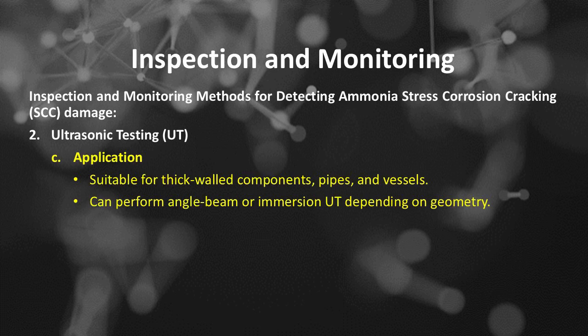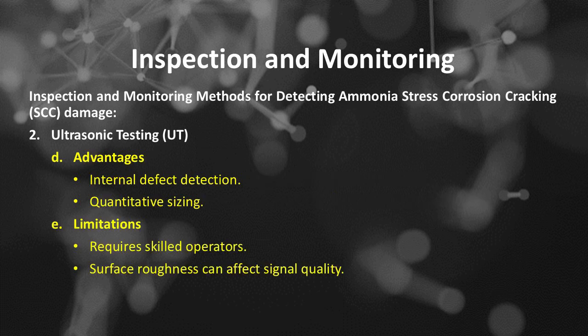Ultrasonic testing, or UT, application. UT is suitable for thick-walled components, pipes, and vessels. UT can perform angle beam or immersion UT depending on geometry. Ultrasonic testing advantages: excellent for internal defect detection, and quantitative sizing. Limitations of ultrasonic testing: requires skilled operators, and surface roughness can affect signal quality.